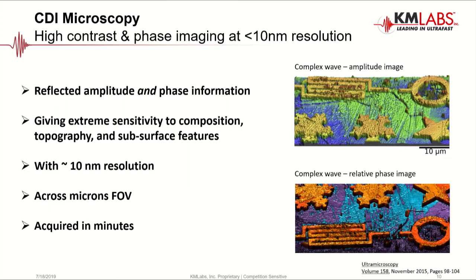So just as a summary, to give the bullet points of what we're doing with CDI, we get both this reflected amplitude and phase. It gives us really nice sensitivity to composition. Remember, we saw those elemental absorption edges on the periodic table I showed earlier. If we can image in the vicinity of edges, we're going to get really nice sensitivity to the chemistry. This is especially true for low Z elements, and that's a place where something like electron microscopy classically suffers when you get down to less than 5 or 10 atomic number.